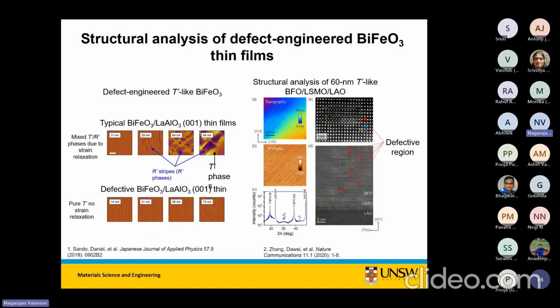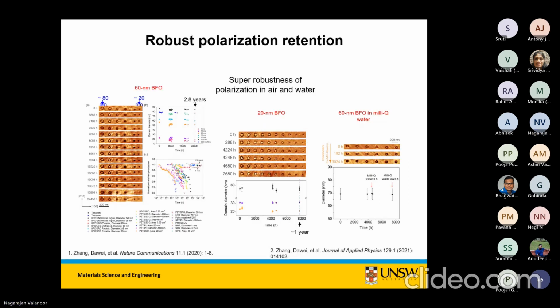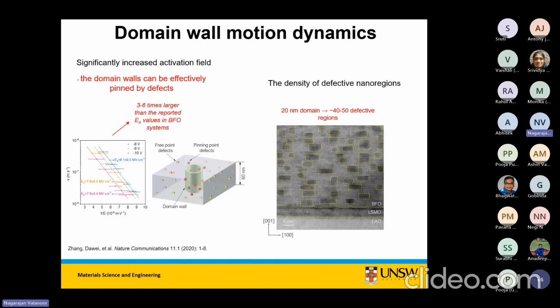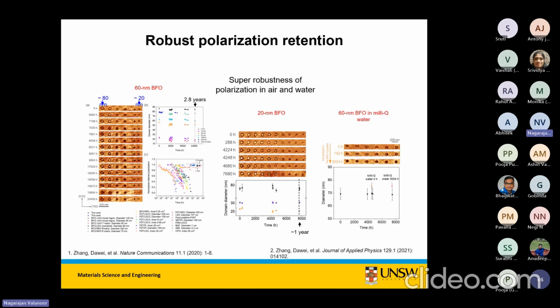Yeah. So you take this system and start to write the bit on this system. We found that those defect pockets actually stabilize. They are pinning centers for your bit. So our retention time, the activation energy for that retention, is about 6 times. And then the student basically came back after a year and he still found those bits written. He was doing some other experiment. He said, okay, I had some time, I'm going to do a PFM, and he found those bits are written.